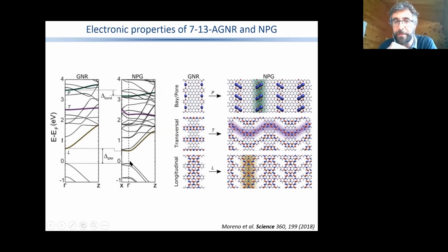The transversal ones, on the other hand, still don't disperse in the longitudinal direction, but now they can couple in the transversal direction. Because the wave function is localized also in the connectors, okay? So once they couple to each other, they can disperse in this direction. So we have states with opposite anisotropy here, or bands with opposite anisotropy.